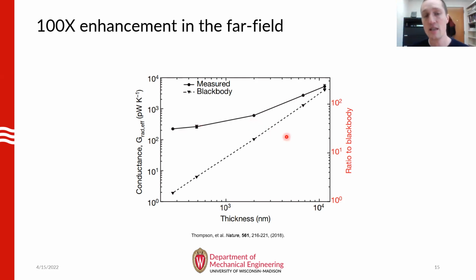As you can see, for the thickest membrane, the measured conductance and black body conductance actually agree quite well. But there start to be large deviations between these two curves as the thickness drops. The red curve here plots the ratio between these two curves for each thickness. And for the thinnest membrane, which is 270 nanometers thick, you can see that the black body conductance underestimates the measured conductance by over 2 orders of magnitude.